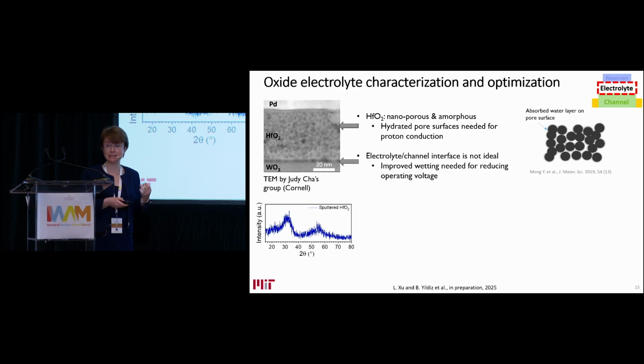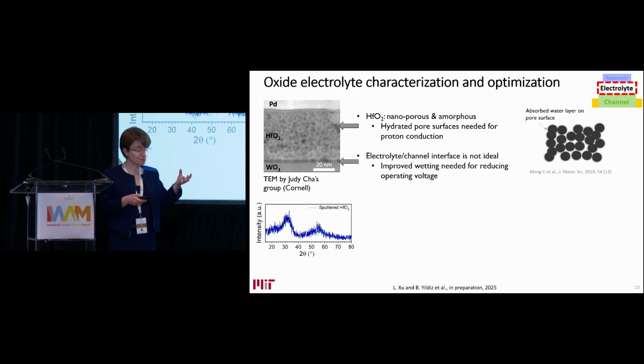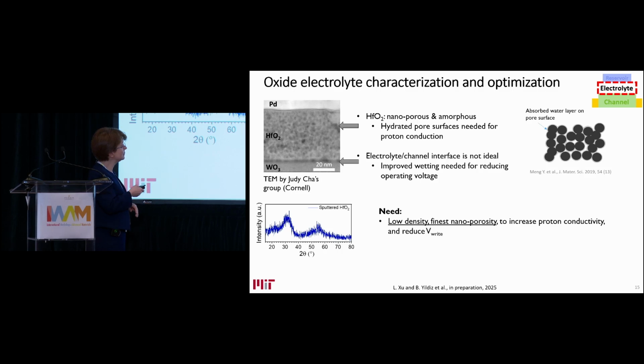So these inorganic electrolytes, like silica, hafnia, zirconia, as I said, they are actually not proton conductors in the lattice. They are dead insulators, but they become proton conductors if you make them bad. So disordered, low density, ideally at the border between nanoporosity and low density. And they become proton conductors in this microstructure because the low density regions or nanoporosity can absorb or adsorb water, OH groups, and that becomes the path for proton conduction. And so ideally you need the lowest density and finest nanoporosity to improve the proton conductivity of these types of microstructures. And we are working in that direction.